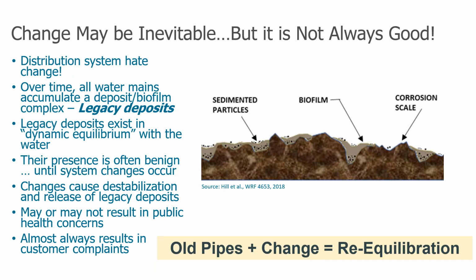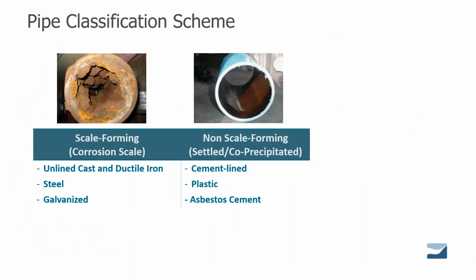So what we have to remember is that we have a lot of old pipes out there, and when we do a change, we're going to have a reequilibration process. It's during this reequilibration process that we can really start getting into some trouble. So I want to start with a pipe classification scheme. I'll be talking about some of these terminologies in the presentation, where we talk about scale forming pipe, and that's where the pipe itself can form often dense corrosion scales from interaction with the pipe material itself. This is our unlined cast, unlined ductile, steel, galvanized pipes. Compared to non-scale forming pipes, where the material that is present has either been settled or co-precipitated or adsorbed, it's not from the pipe material itself. And those are often our cement-lined, plastic, and asbestos cement pipes.